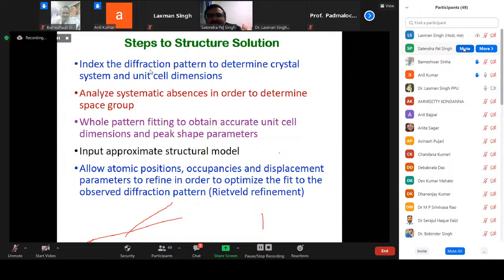Okay. So, if you have unknown systems, then what are the steps involved for the structural solution? First, index the diffraction pattern to determine the crystal system and the unit cell dimensions. Second, analyze the systematic absences in order to determine the space group. Third, full pattern fitting to obtain accurate unit cell dimensions and peak shape parameters. And then input an approximate structural model, allowing atomic positions, occupancies, and displacement parameters to be refined in order to optimize the fit to match the observed diffraction pattern, and this is done in the Rietveld refinement. So these are the steps.